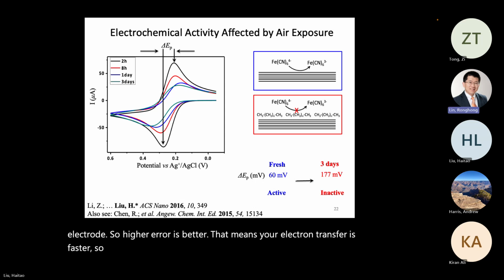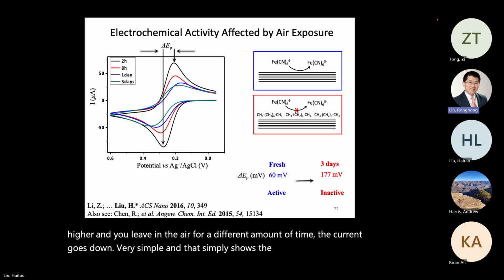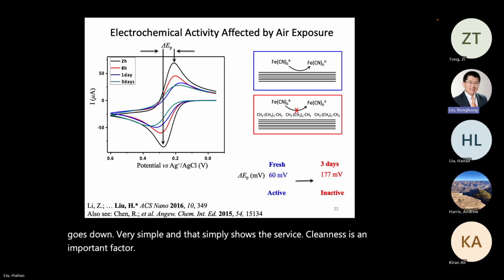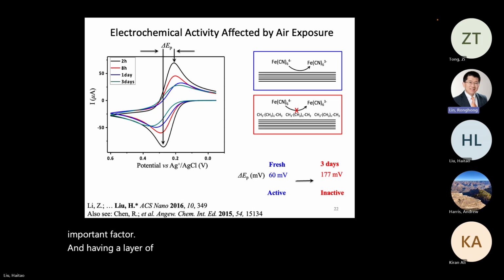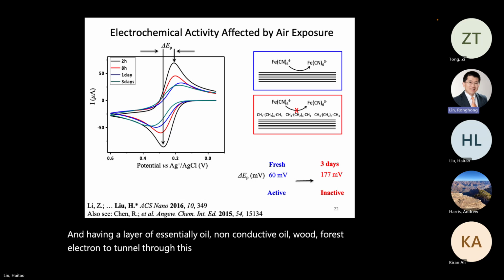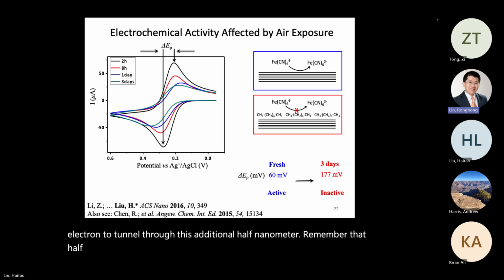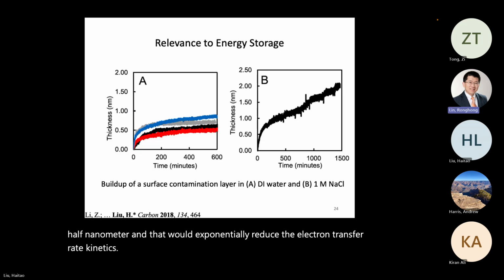So what you see here is freshly exfoliated graphite. The current is high, and you leave it in the air for different amounts of time, the current goes down. Okay, very simple. And that simply shows surface cleanness is an important factor. Having a layer of essentially non-conductive oil would force the electron to tunnel through this additional half nanometer. Remember that half nanometer. And that would exponentially reduce the electron transfer kinetics. I'm going to skip this one.